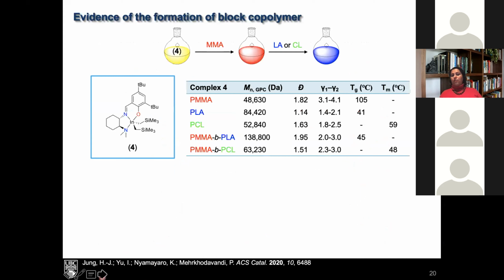We formed the copolymers, and so now the question isn't just that we've added the two monomers and formed a copolymer. The question is, did we make the copolymer, and what kind of copolymer did we make? So we had to really do our homework in trying to understand whether we were making, in fact, a block copolymer. So the first thing that we looked at was GPC. You can see the molecular weights for the homopolymers are uniformly, under the same conditions, lower than the molecular weights for the block copolymers. But since this is not a living system, as opposed to our beautiful first story where everything was perfectly living, it's not enough. This is not enough to convince us.